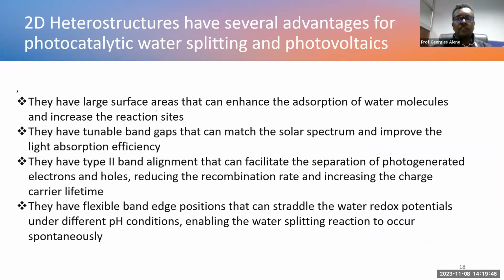2D heterostructures have several advantages. One, they have large surface areas that can enhance the adsorption of water molecules and increase the reaction sites. They have tunable band gaps that can match the solar spectrum and improve the light absorption efficiency. We will also see they have type 2 band alignment, and this type of band alignment is good for separation of photo-generated electrons and holes. And they have flexible band edge positions that can straddle the water redox potential under different pH conditions.